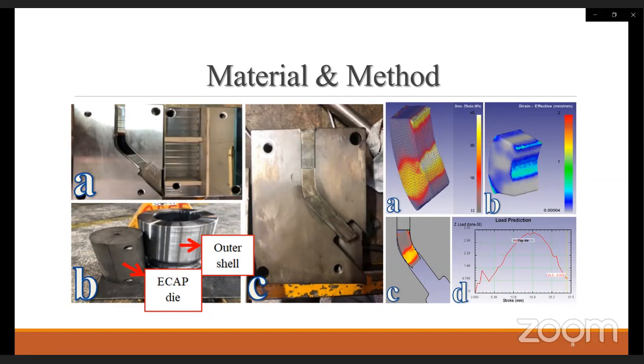After all these works are finished, the die is assembled carefully. The outer shell is also assembled on the die to prevent it opening during the operation. The channel has a cross-section with the lengths of 19 mm for each side of the channel. Hence, the samples are machined to 18.95 mm in the cross-sectional dimension and 40 mm in longitudinal dimension. Then the ECAP die is assembled as shown. We have assembled this ECAP die into this outer shell.